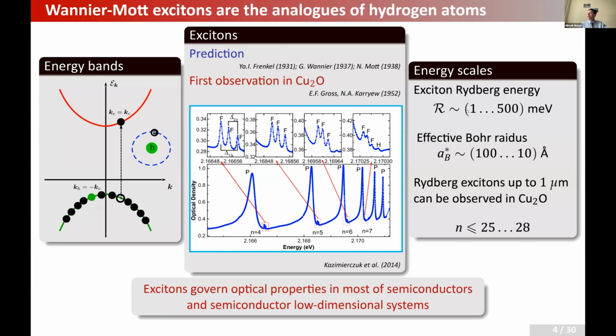Their binding energies can range from units to hundreds of milli-electron volts. Correspondingly, their effective Bohr radius, the effective size, can be in the range of hundreds of angstroms to tens of angstroms, again depending on the materials. In some cases, like in cuprous oxide, you can highly excite excitons, promoting them to states with large principal quantum numbers, so that these excitons become really big objects with diameters typically on a micrometer scale.